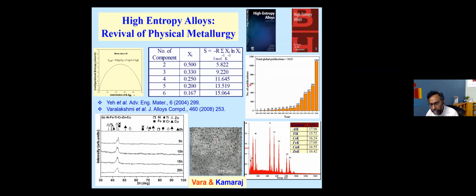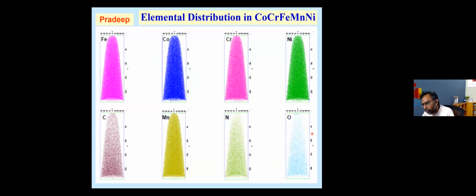And if I take any particle and put an electron beam on that, by a technique called energy dispersive spectroscopy, I can find out the elements present and their composition. You can see each of them is very close to 16%: 16, 15, 17, just within 1% error. Okay, the composition is so uniform. And such a material can be made, and it has wonderful properties. We can also use atom probe to see how uniform these elements are.